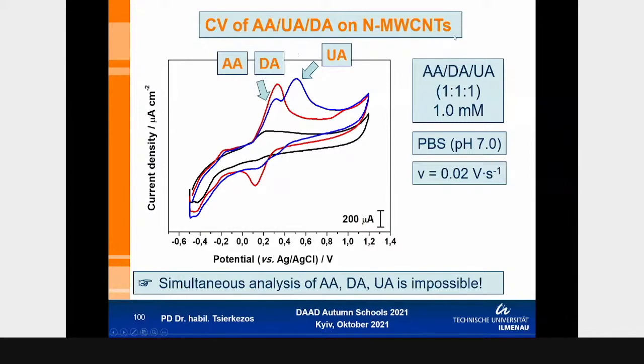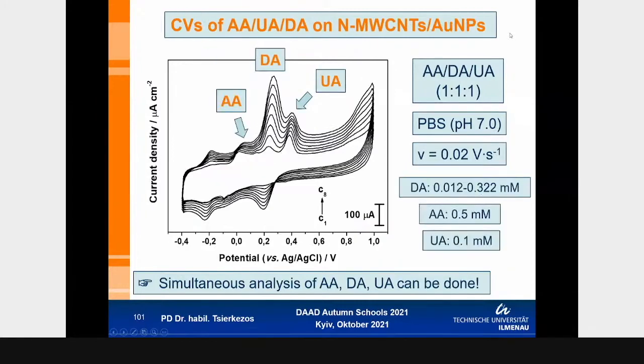So we have done the following. We modify them with gold nanoparticles. We take this material and we place gold nanoparticles on the surface, and then we observe this behavior. We observe a peak for ascorbic acid, a peak for dopamine, and a peak for uric acid. And it's important to say that the potential for oxidation of ascorbic acid is shifted to the negative area, which means that it lies at about 0.05, I would say, instead of 0.2, and this leads to a good separation of both peaks of ascorbic acid and dopamine. So we can say that on this material, the simultaneous analysis in one measurement of these 3 compounds can be successfully done.